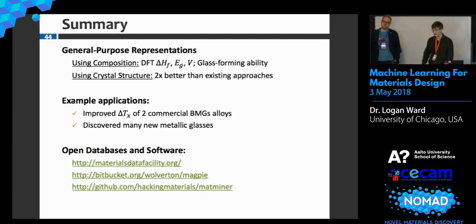Yeah, that's a really good question. We find that for very large data sets, using any approach to reduce the dimensionality, to cut down the number of attributes in the model, doesn't have a marked effect. I started with saying for large data sets, because once we have smaller than a few hundred or maybe even a few thousand entries, employing some kind of feature selection technique can significantly improve the accuracy of the model. Here, we actually use functionality from random forest to do that. We use its descriptions of what are the most accurate variables and use that to gradually refine the space.